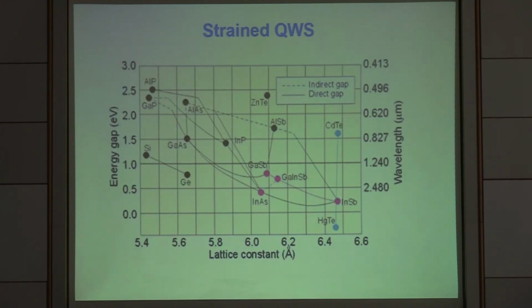Now we want to do something completely different, moving away from this. Whether we can reduce the interaction by changing the Fermi velocity. One way to do it is to emphasize the energy gap. If we make the energy gap much bigger, of course the Fermi velocity is going to increase automatically, right? That's one of the things to look at. So this uses a technique called strained layer.